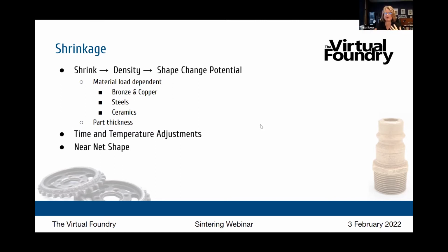Go ahead. When we talk about the shrinkage being material load dependent, when you follow the instructions that we have posted on our website, the bronze and copper are going to be around 5 to 10%. The steels are going to shrink a little bit more, because they have a little bit lower material loading. And the ceramics, especially the 46D ceramic clay, have a much lower material loading by mass. So that one's going to shrink a lot more, more like 40% following the instructions on our website.